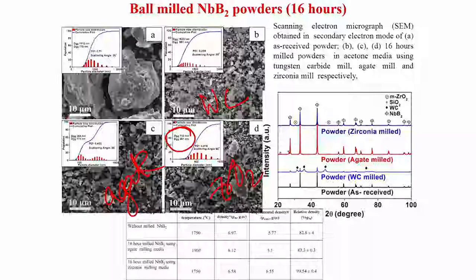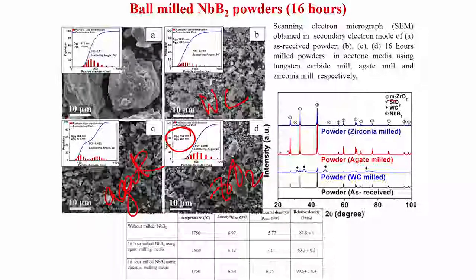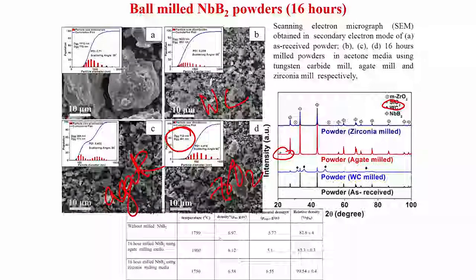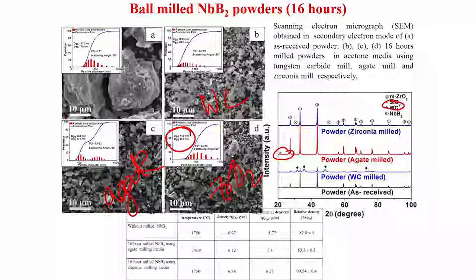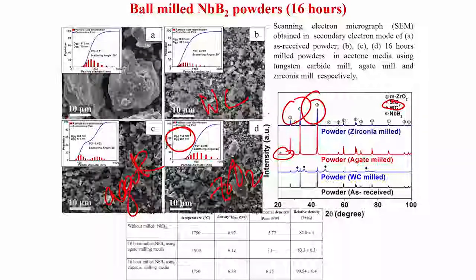If you see the X-ray diffraction patterns, you will see that the contamination from silica is quite extensive in the agate case, and tungsten carbide milling media also shows small amounts of tungsten carbide present, while niobium boride is quite significant in all these cases.